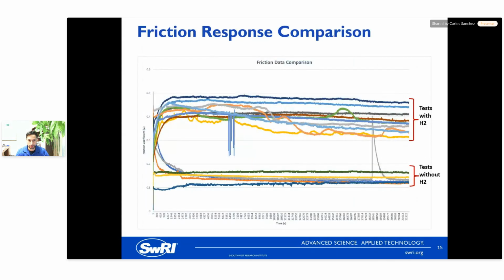So getting more into the test results. This is a fairly messy graph, but I just wanted to give you an idea of tests with and without hydrogen. So we tested with hydrogen here, which are all the higher friction. These are plots of friction coefficient over time for a 6 hour test. Like I said, with that 3 hour prior soaking for the hydrogen, and then we ran the test here. For the test without hydrogen, there's a mix of ambient conditions, and also some where we ran pressurized with nitrogen just to see if there's any issue there. But in either case, either without the hydrogen in ambient or with nitrogen present in the environment for that cell, we didn't see a significant jump in friction coefficient like we did with the hydrogenated test.